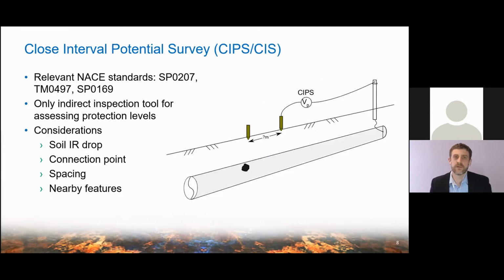Now let's look at CIPS. The Close Interval Potential Survey, or CIS, is referred to or described in NACE standards SP0207, TM0497, and then the criteria in SP0169. And SP0169 is the criteria like the -850 millivolt CSE, polarized potential criterion, and the 100 millivolt criterion. And those are the things that we use for assessing protection levels.